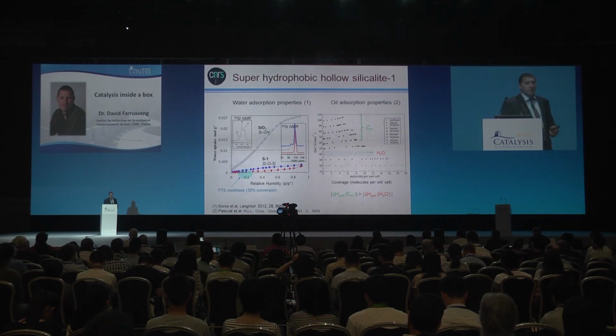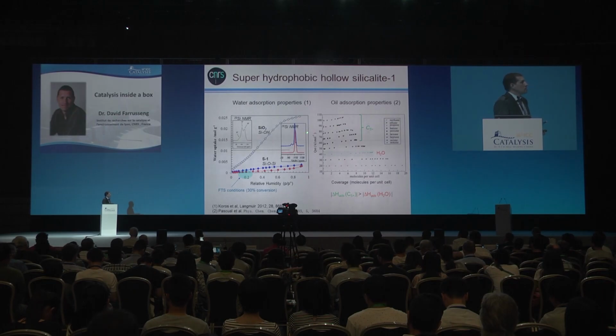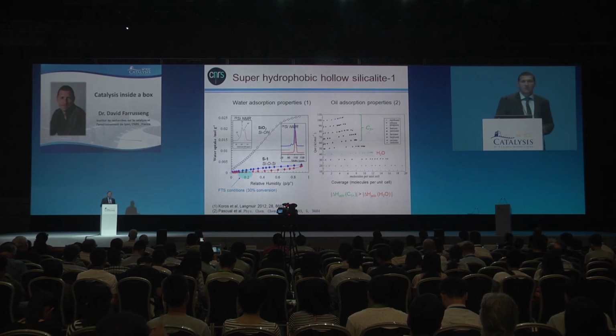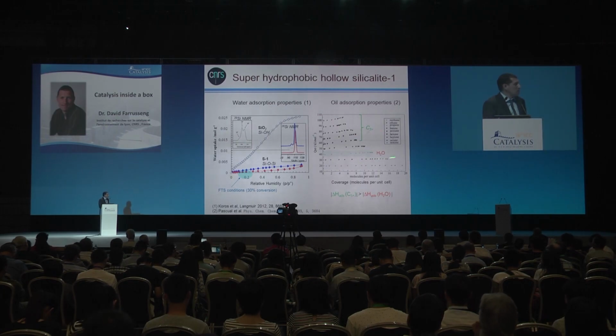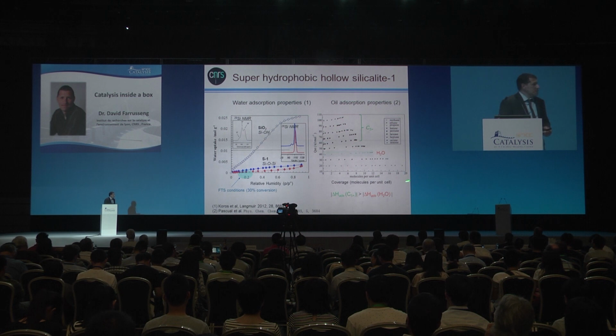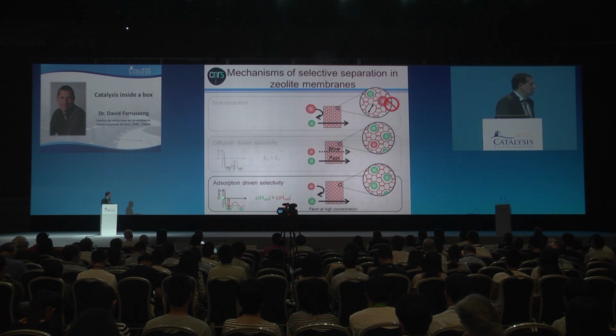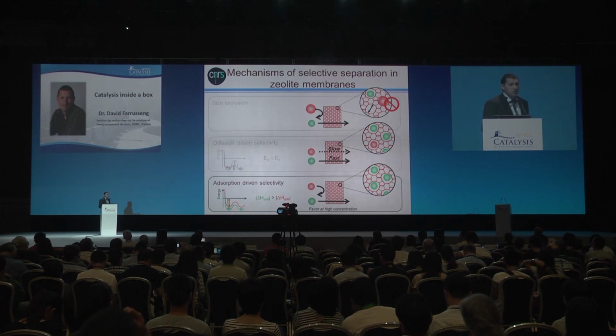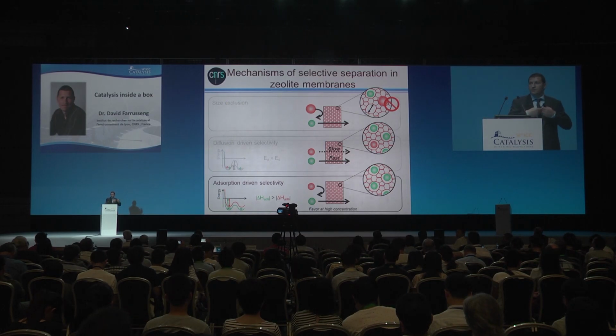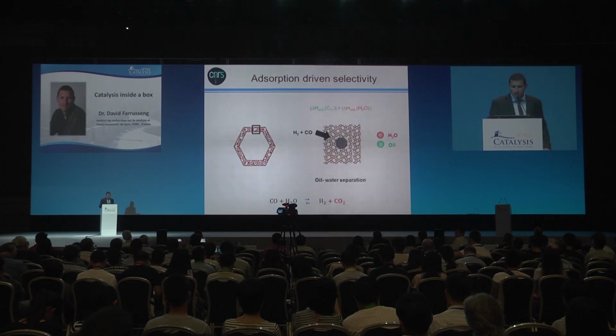And on the opposite, of course, if we don't adsorb water, this type of membrane likes very much to adsorb oil. You can see here the heat of adsorption of the liquid fractions, pentane, hexane, and so on, with a very high adsorption strength on the zeolite, much higher than the water. It means that we are in the case where one component has a much higher adsorption strength than the other, and obviously it will push the water out of the membrane.